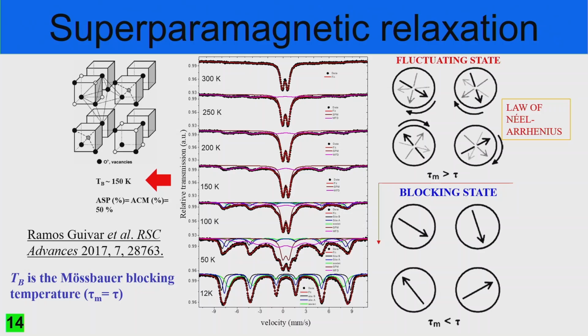But the problem when characterized magnetically is that we can find, of course, fluctuating states, a relaxed spectrum here at 300 Kelvin. And we cannot get information about the purity, of course, whether this is magnetite or maghemite; a single phase also cannot be determined. I can make an approach near nitrogen temperature, but I can add, as you know, many components here, and I can overestimate the actual contribution from these sites of the spinel. At low temperature, we can also apply the model, but the broadening is still significant. So I will need other techniques like synchrotron, as Professor Valdemar said yesterday, to unravel these properties.